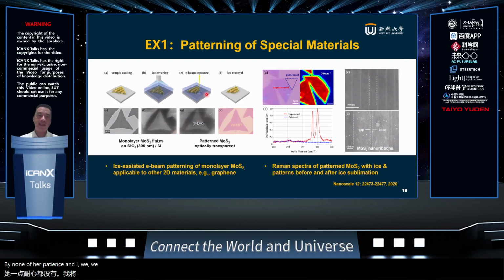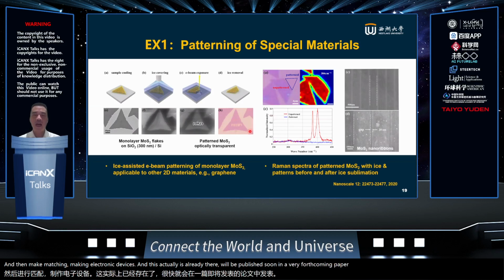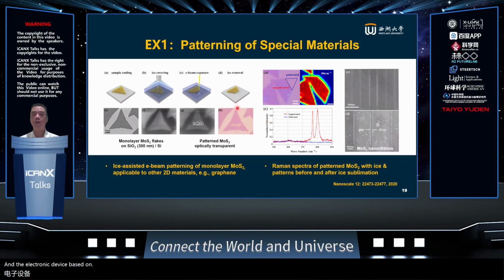And we realized that because they are very sensitive to electrons, if you expose them directly with electrons, you can take them away easily. Then, combined with ice lithography, we can either directly remove the MoS2 using e-beam, or protect it with ice and then take the ice away, then make electrodes on top of it, make connections, and make electronic devices. This will be published soon in a forthcoming paper, on how to make an electronic device based on this using a combination of e-beam lithography plus ice lithography.